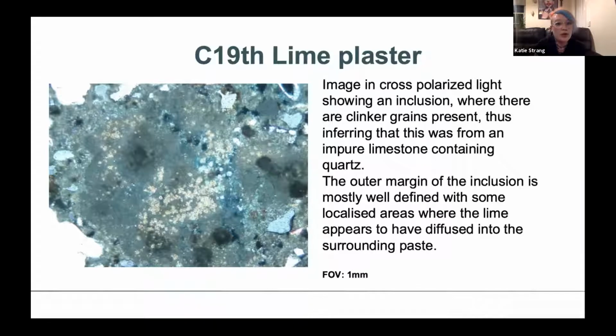But the outer margin of this inclusion here, you can see is quite well defined. And in here is all your big clusters of clinker. But there are areas where it has seemed to have diffused quite well. So there's obviously something going on with the timing of this slaking, where parts of your particle are reacting, but then there's other parts that are not reacting until later on when moisture is getting into the material.